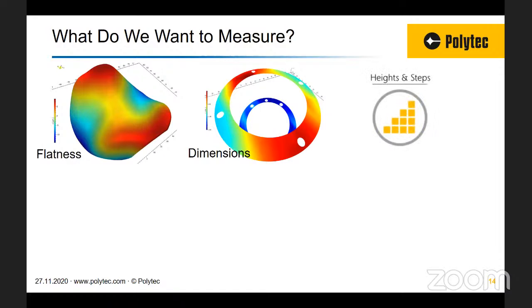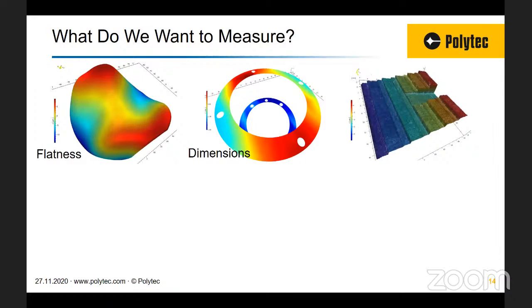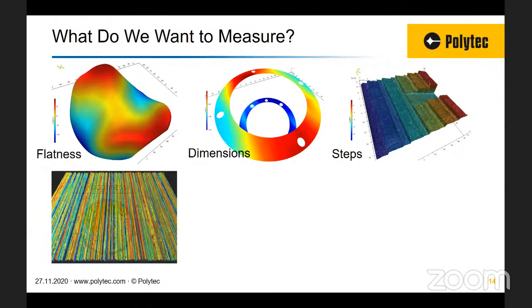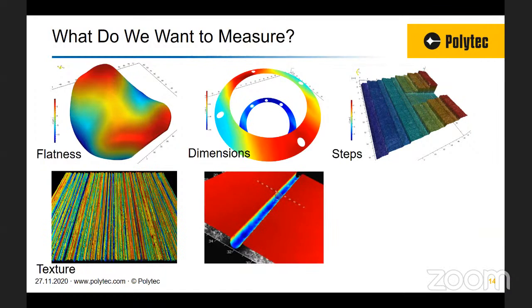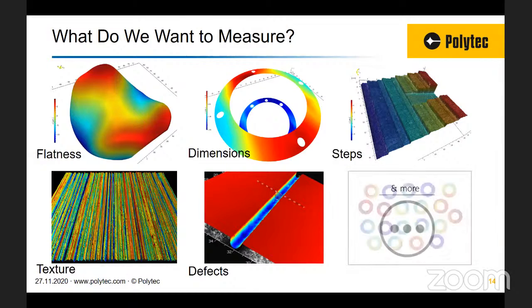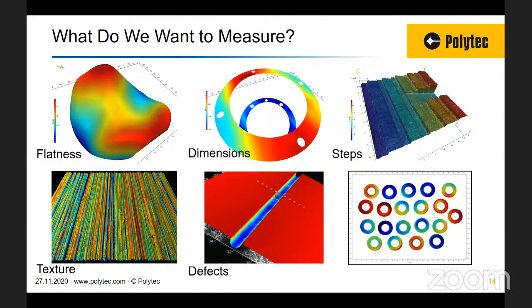We can naturally measure step heights. So here you got a stepped feature, and you can see a machine feed error. So you can measure step height information. Of course, we can measure roughness, and that will present you with surface texture information. And of course, tribology, so looking at scratches and defects of a surface. And finally, we're particularly interested in automated measurements. So if you have multiple samples and they all fit within a single field of view, we can do multiple processing for our pattern matching, and you can have fully automated measurements.